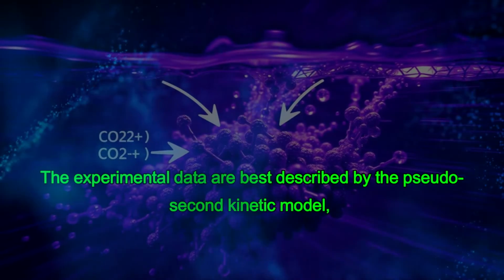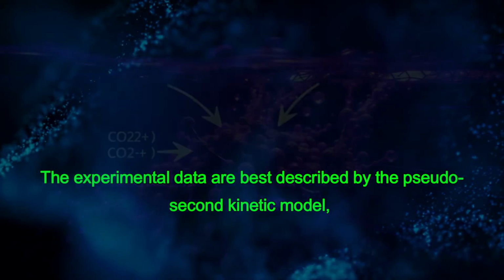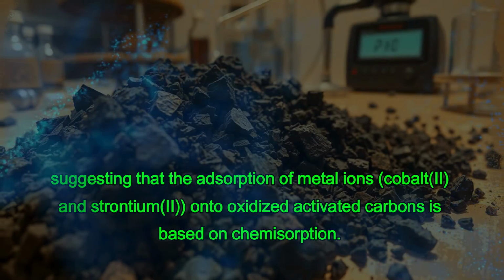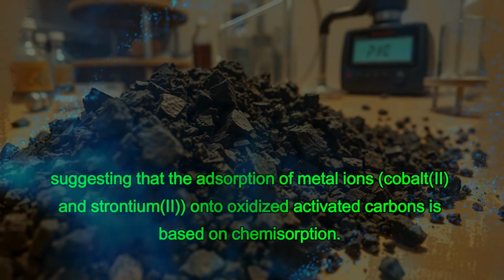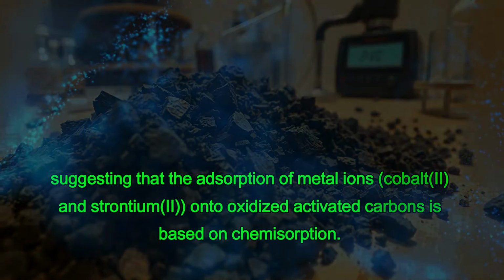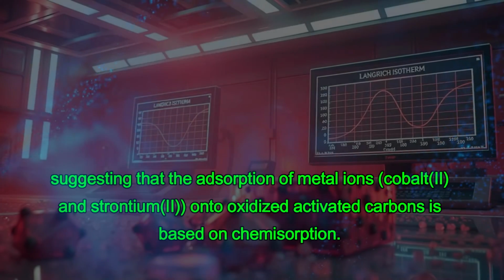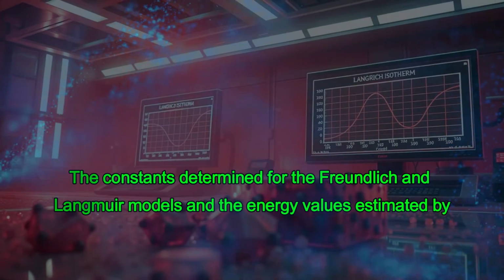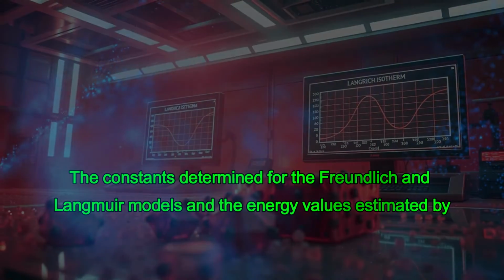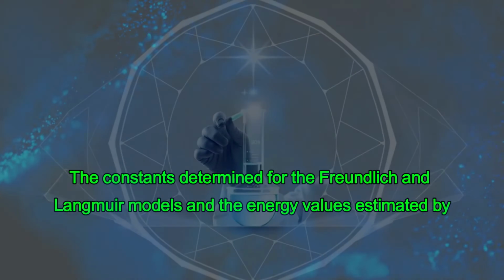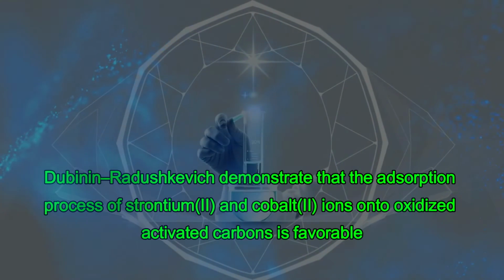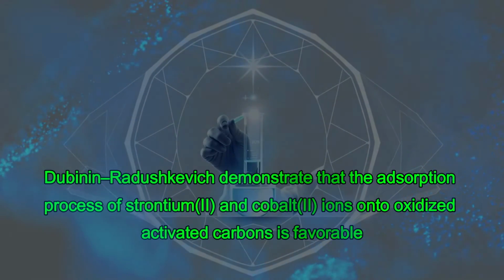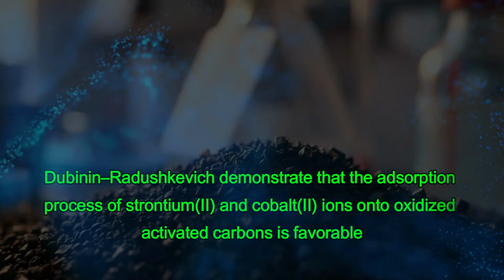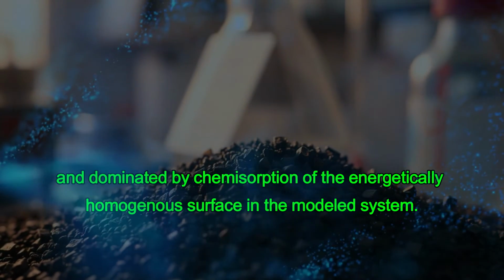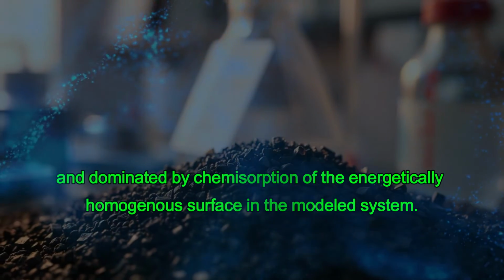The experimental data are best described by the pseudo-second-order kinetic model, suggesting that the adsorption of metal ions, cobalt and strontium, onto oxidized activated carbons is based on chemisorption. The constants determined for the Freundlich and Langmuir models and the energy values estimated by Dubinin-Radushkevich demonstrate that the adsorption process of strontium and cobalt ions onto oxidized activated carbons is favorable and dominated by chemisorption on an energetically homogeneous surface in the modeled system.